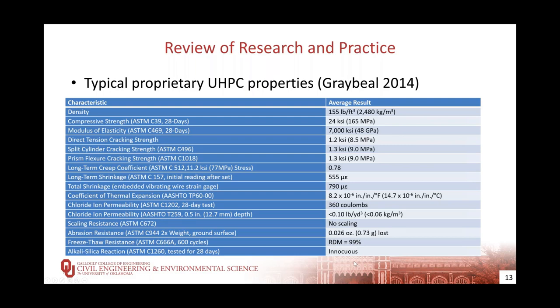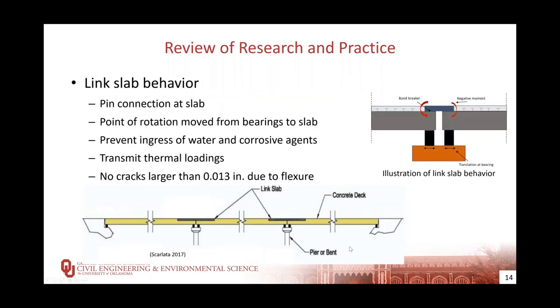In terms of looking at link slabs and reviewing what's been done out there, there's a lot of general guidance that's available on design of link slabs. But the behaviors that we're looking for are that we get a pin connection at the level of the slab. And so instead of having all the rotation at the bearings, that rotation moves to the slab joint. It creates a cap over the beams to prevent the ingress of water and corrosive agents. And even though we may get some cracks, we don't get that large opening like what we see for an expansion joint.